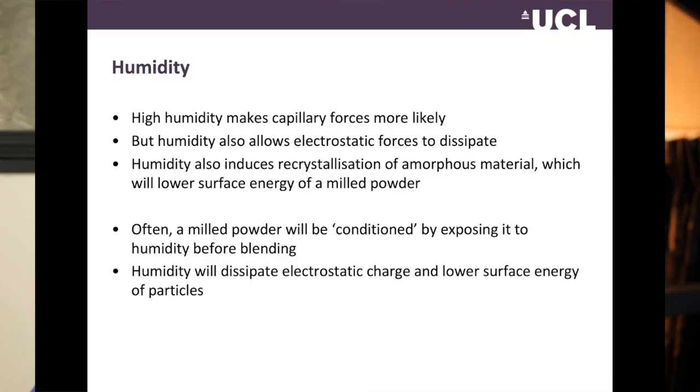And so that's a really tricky situation, because if those two materials are partially amorphous at the surface, water will also act as a plasticizer for that amorphous material and encourage it to recrystallize. So if we have a relative humidity above 65 to 70%, for instance, this becomes the dominant force, more important than electrostatic charges. High humidity is both good and bad. If humidity is too high, then we get liquid bridging and our particles stick together. But if we have a reasonable humidity, it can also cause electrostatic charges to dissipate.